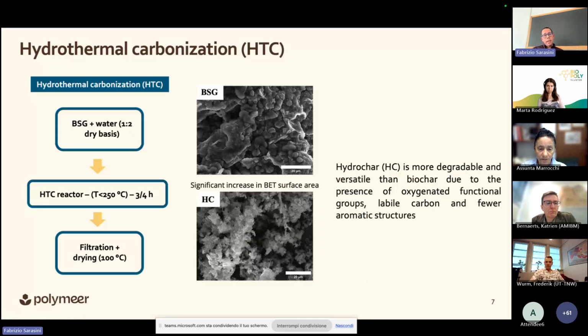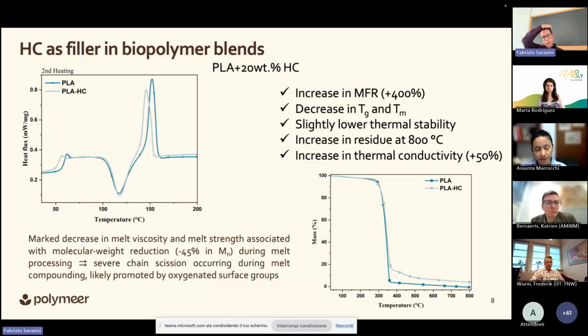I also need to mention that hydrochar is much more degradable and versatile than biochar, and this is mainly due to the presence of oxygenated functional groups on the surface, and also a lower aromatic structure. This is particularly important if you want to use it as a filler in polymer blends. So at the very beginning, we decided to check the effects of this filler in a very standard and common bio-based polymer, polylactic acid, and we used a pretty high amount, 20% by weight, and we detected a few important results.